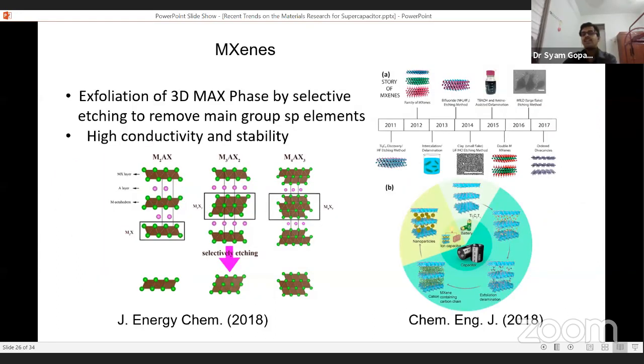And another new material which has emerged, a hot material nowadays, is MXene. It consists of a MAX phase, usually titanium aluminum carbide, and if the aluminum phase can be etched out, then we can synthesize a titanium carbide material, which is a layered stacked material. The biggest advantage of this MXene is its stability, as well as accessible sites for electrolyte ions, thereby having pseudo-capacitive property.